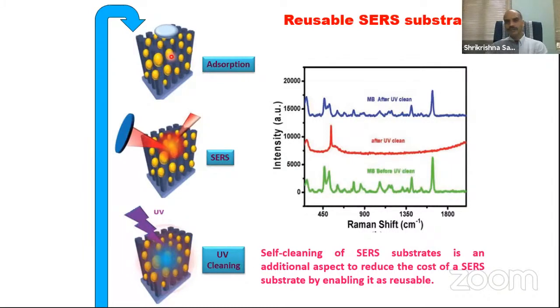I will measure, for example, this methylene blue before UV cleaning, and I will get this particular intensity. Then I will use this UV cleaning. So I will incident UV radiations on that metal nanoparticle coated on zinc oxide or TiO2 nanotubes or whatever. Then I see no intensity here. You see that this methylene blue intensity is almost 0.